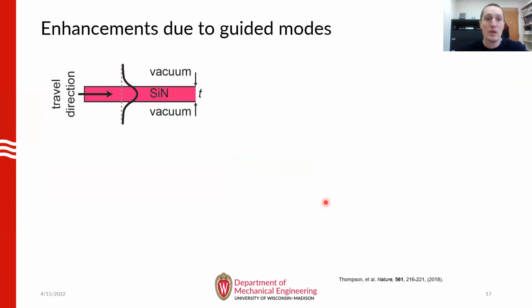It turns out that we get these large enhancements in heat transfer due to the specific shape and orientation of the nanomembranes. Because of their high aspect ratio, these membranes are similar to a slab waveguide, illustrated on the left here. Any slab waveguide can support what are called guided modes, which are electromagnetic waves that propagate through the slab and exponentially decay outside of the slab. These modes can be TE polarized, where the electric field is in plane, or TM polarized, where the electric field is out of plane.